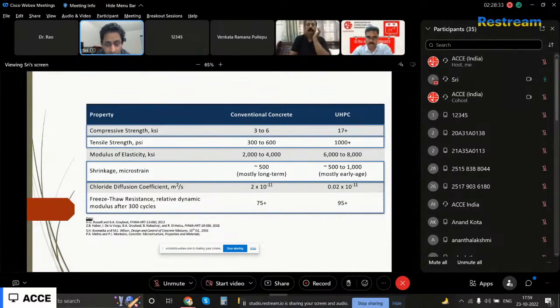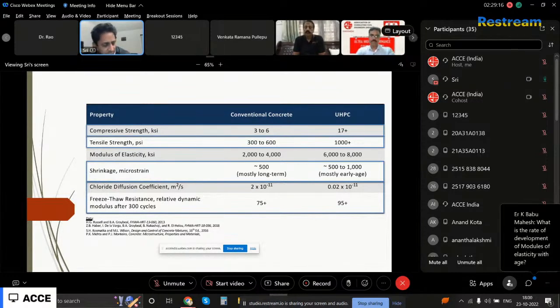Traditionally, the tensile stress before cracking is the most important part of a design to decide how much steel goes into the structure, which Mr. Prasad Garu, you were asking some time back. So how do you decide? Take it as approximately 2 to 2.5 times. Your tensile stress before cracking is 2 to 2.5 times more than conventional concrete, essentially. So in conventional concrete, probably 600 psi. Give me 1 second. 600 psi is how many Newton per millimeter square? 600 divided by 145, you get around 4 Newton per millimeter square, approximately.